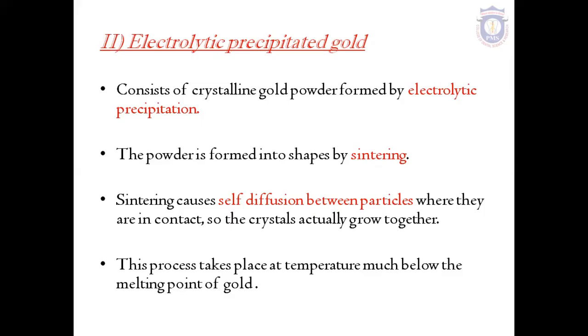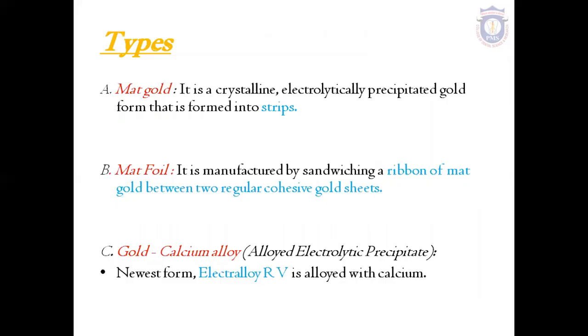That is, by electrolytic precipitation, crystalline gold powder is formed, and it is formed into shapes by sintering, that is, heating at a high temperature but below the melting point of gold, and this causes self-diffusion between particles and the crystals grow together. Types: matte gold, matte foil, and gold calcium alloy. Matte gold is a crystalline gold which is formed into strips. Matte foil is a ribbon of matte gold between two gold sheets, and gold calcium alloy is an alloy of gold with calcium.